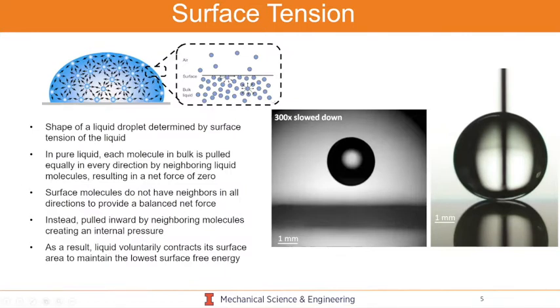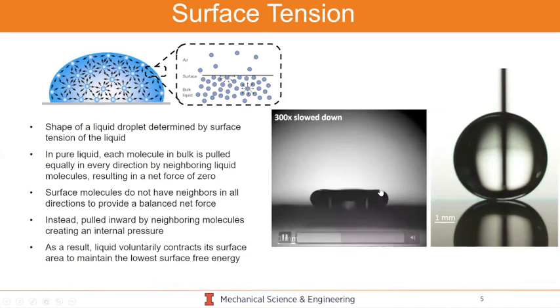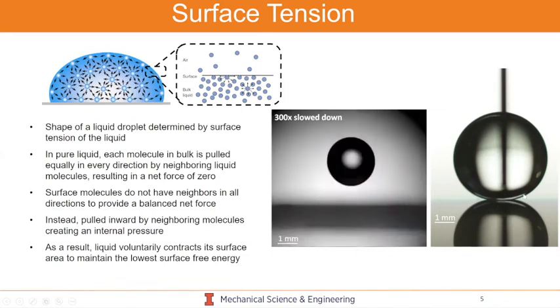And so what you could do with this is actually tailor surfaces to utilize this property, especially for higher surface tension fluids, to have non-wetting, in this case a droplet hitting a superhydrophobic surface, and have these highly spherical non-wetting states. So this is actually a needle which injects liquid water, and this down here is a superhydrophobic silicon wafer with a surface structure called black silicon that's been functionalized.